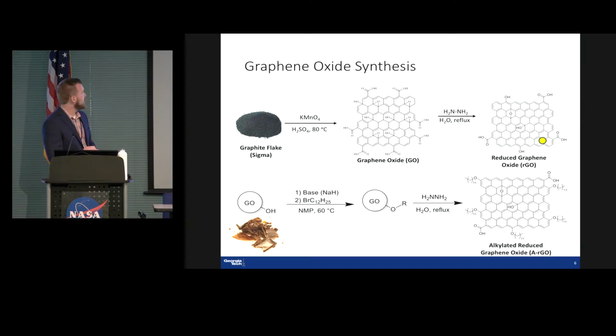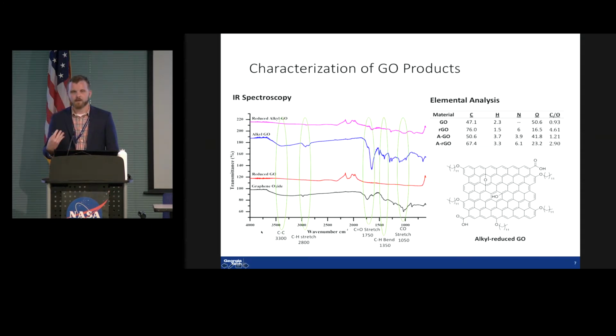What I'm going to do is take this product here and use it as a starting product to do this alkylation reaction, and then I'm going to reduce that further. And we can see a clear difference. This is graphite flake. This is what I start with, and this is the graphene oxide product that I would synthesize in my lab. And so with this, after we've done this synthesis, it's tricky, but we can do a few different things to confirm that we've actually successfully completed these alkylation reactions.